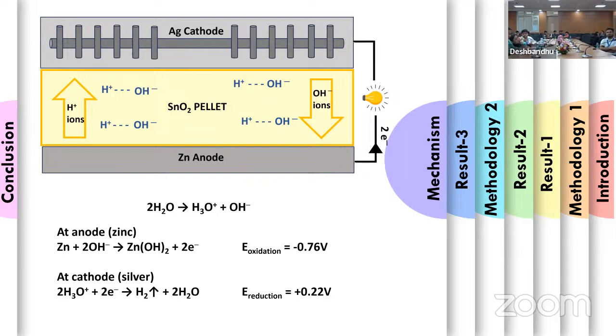Due to the presence of pores, the H3O+ ions adsorbed in the pores generate a high electrostatic potential in the range of 10 raised to the power 4 volts, which is high enough to dissociate the water molecule into H+ and OH- ions. As we can see here, the OH- ions go to the zinc anode, which takes up 2 OH- ions and forms Zn(OH)2, releasing 2 electrons. These 2 electrons go to the silver cathode, and here the H3O+ ion takes up the 2 electrons and releases H2 gas.